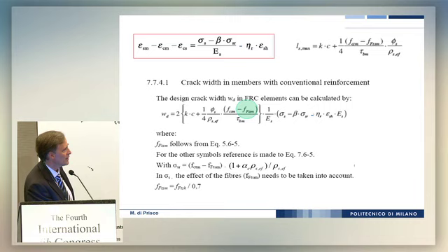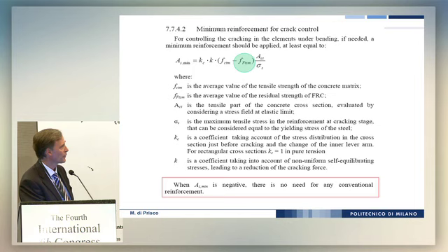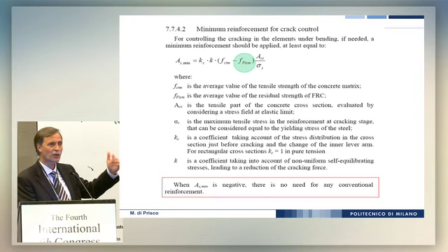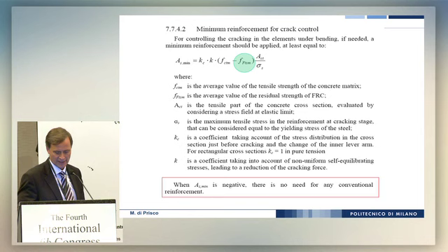You remember that this part represents only the crack spacing, and this part essentially gives us the average strain in the steel. And you have also a contribution in the minimum reinforcement for crack control, and so we always use the ultimate limit value. It's important to highlight that the crack opening is not always the same. So for instance, if you have shear, the ultimate crack opening is 1.5 millimeter and not 2.5. If you have other situations, you can have different crack opening values.